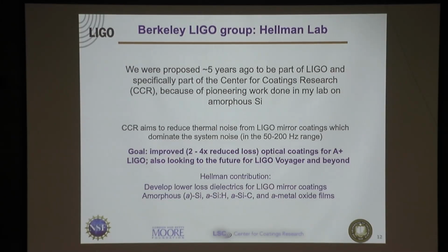But by an interesting thing that has been known for quite a while, it's quite easy to make it by vapor deposition processes. And so there was a reason I was working on this, but it was not about LIGO. But we did discover that we could make enormously reduced noise material by sort of serendipity. We were looking at something else and discovered this. So what we're trying to do right now is improved optical coatings for A+, sort of 2 to 4 times reduced loss. And my particular contribution is to try and take advantage of what I've already done in amorphous silicon and see if I can expand it into some other even more useful materials.